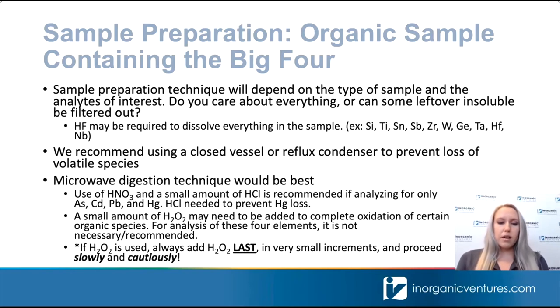But we recommend avoiding use of hydrogen peroxide if possible, as it is very dangerous to work with, or can be. So if you are using hydrogen peroxide, make sure that you're always being very careful and adding it last after all of the other solution components or the other acids to make sure that you're not getting a buildup of hydrogen peroxide, as this can cause actually an explosion.